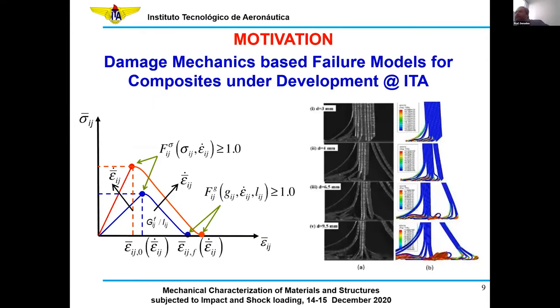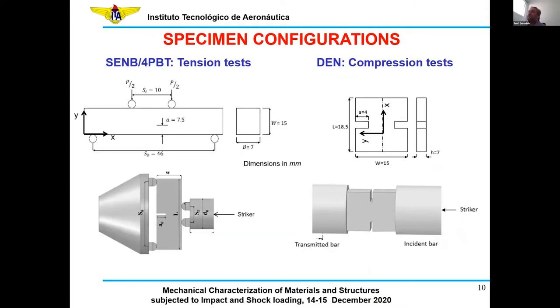One of the critical points here to use this approach, as I mentioned before, is that we have to characterize the critical strain energy release rate to build up or to define our propagation criteria. As you may know, most of the tests that we have right now for metallics to measure this property are not standardized for composite, particularly if we perform high strain rate tests. Within this context, we have spent some time trying to design some suitable specimens that allow the characterization of such properties for composite.